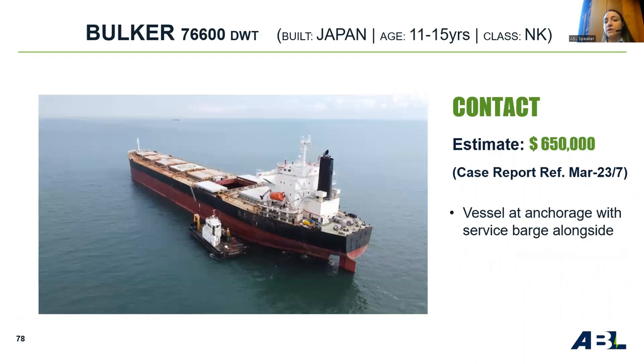Finally, we have another bigger Panamax-sized bulker that has also suffered from contact damage, but this time below the waterline and with no particular incident that has been identified or admitted to link this with. The story is that the vessel arrived in ballast at the anchorage port in the Americas and was at anchor, awaiting loading instructions. From regular tank soundings, a water level change in the number 4 ballast tank on the starboard side was detected.